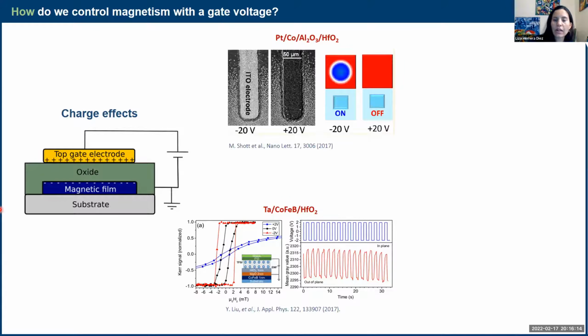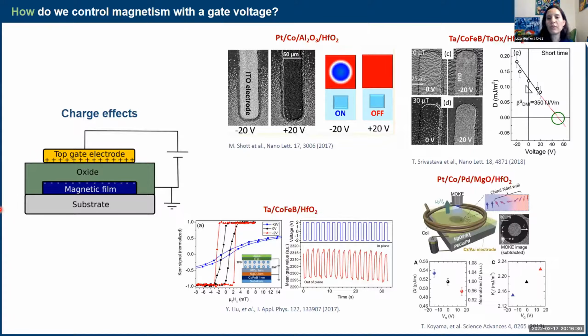And then there's this very nice work by the people in Grenoble, so in France. So they could switch on and off skyrmions in platinum cobalt thanks to the gate voltage. And also people have looked at DMI. So I mentioned before that DMI is a lot related to your bottom interface, but of course it's related to the asymmetry between the two interfaces. So then you could still have a shot at changing DMI if you control the top interface. And this is what they did. So they used this charge accumulation to modify DMI. In both these studies, they could see how that affected domain wall dynamics. And then as you can see here, they could also see skyrmions, etc. So there are very nice things that can be done with charge effects as well.